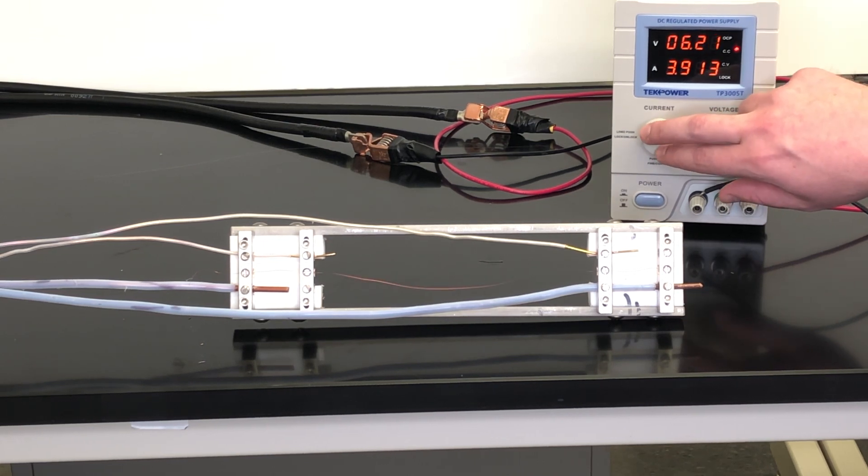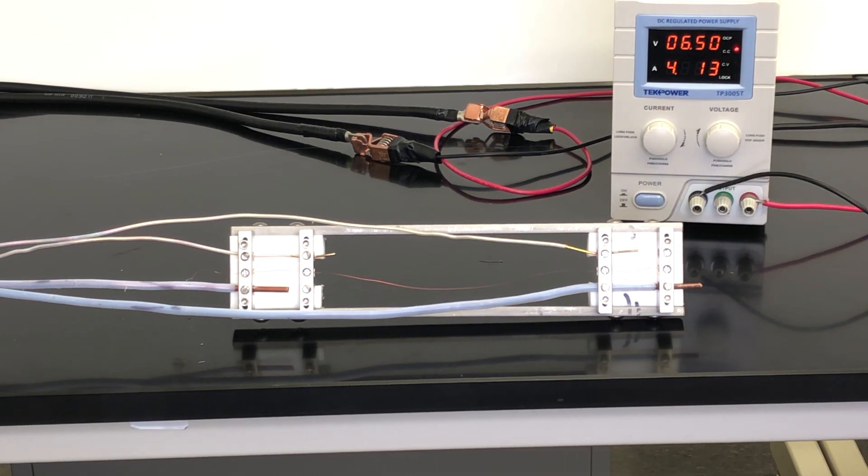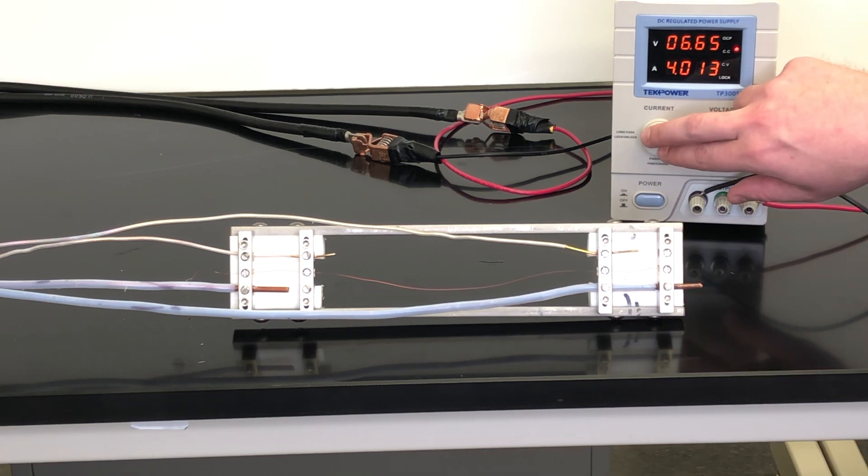This wire sustained a current up to around 4 amps, and then at 4 amps, you can see the voltage starts to rise uncontrollably on its own, and the wire enters a runaway heating cycle, finally reaches a temperature at which the copper melts and the wire breaks.